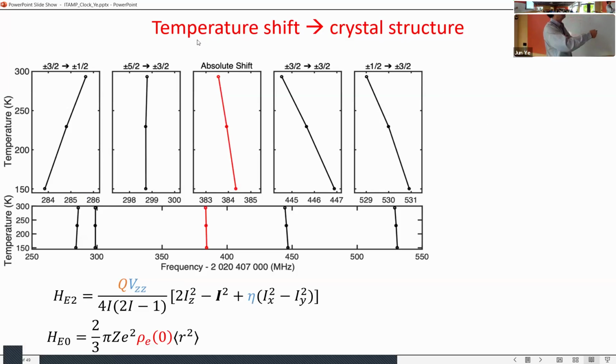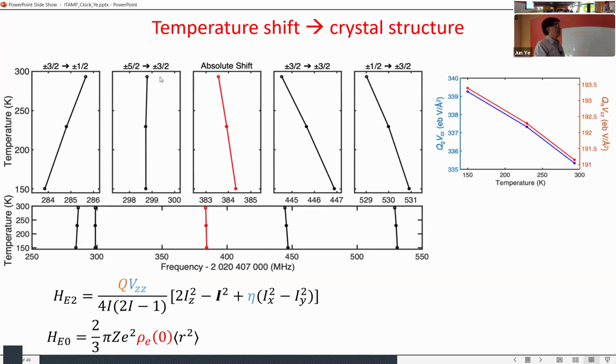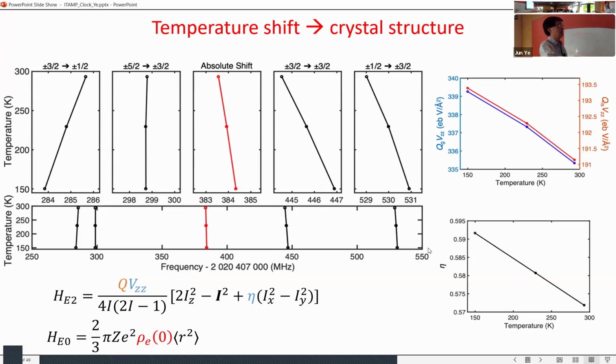And so indeed, as we change the temperature from room temperature to 150 Kelvin, you can see different transitions move differently. And there's a particular transition, for example, that has accidental cancellation between the electron charge density change and the nuclear quadrupole moment change. You can get to the point where it's hardly dependent on the temperature. And so you can plot the nuclear quadrupole moment times the electric field gradient as a function of temperature, or you can plot the asymmetry parameter eta as a function of the temperature. But together with the sum rule, you can actually calculate the quadrupole shift. You can sum them in certain ways where the synthesized center of frequency does not depend on the quadrupole shift. And that frequency can still move.